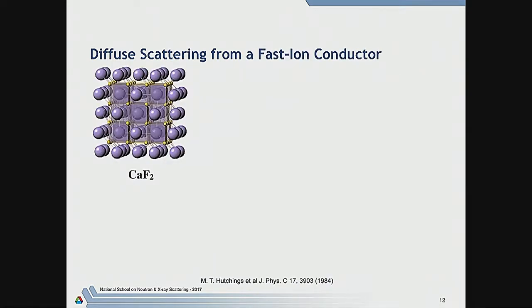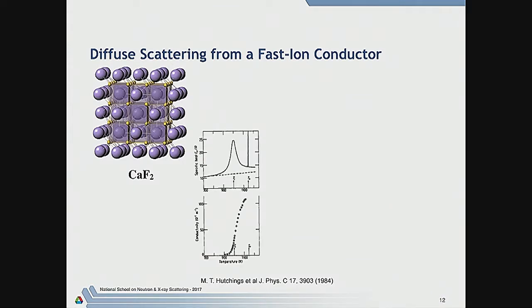One that I was involved in, in the early 80s, was diffuse scattering from fast ion conductors. For example, in fluorites like calcium fluoride, strontium fluoride, and uranium dioxide, which is the reason Harwell was interested. They go through what's called a superionic transition, where the mobility of the anions suddenly goes from very low to almost the same as in the melt. So it becomes a fast ion conductor above a certain temperature, and you get a big peak in the specific heat. This was called sublattice melting at the time, although it's not really melting. The space group doesn't change. They're still in an ordered grid. But there clearly is a lot of disorder and a lot of mobility of these ions.